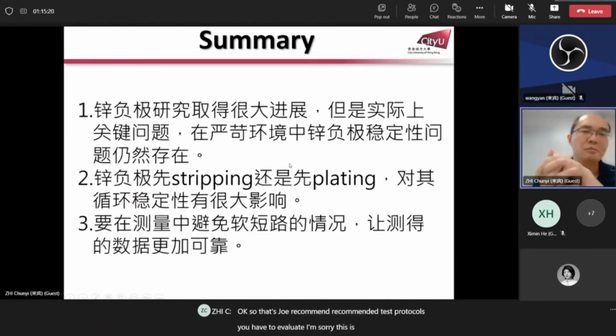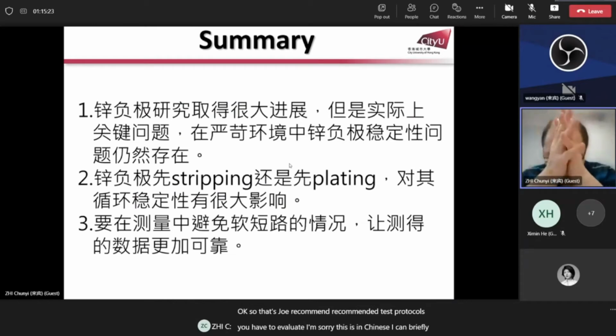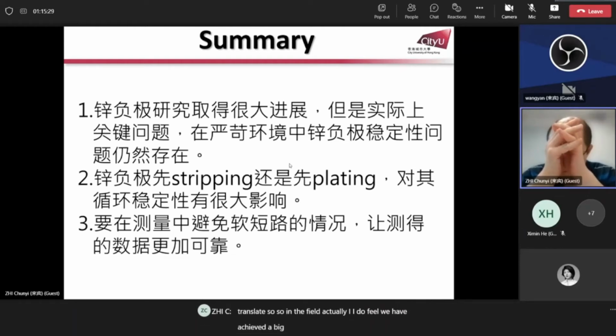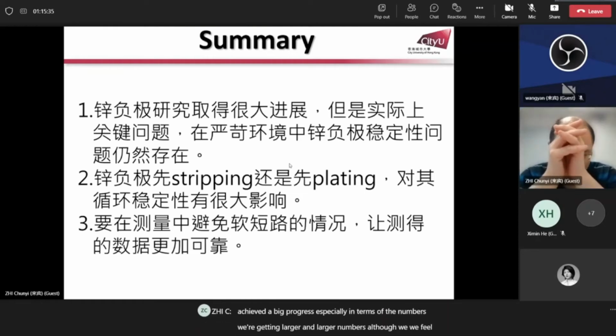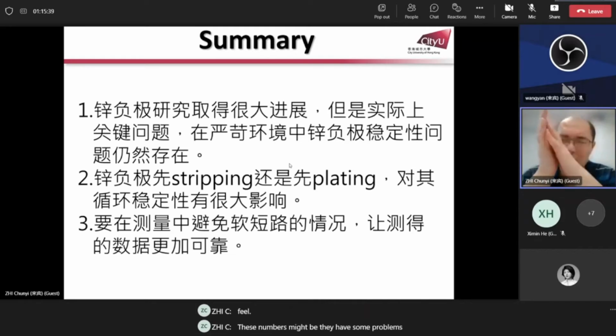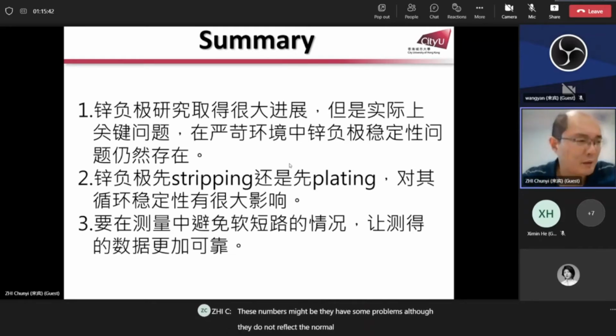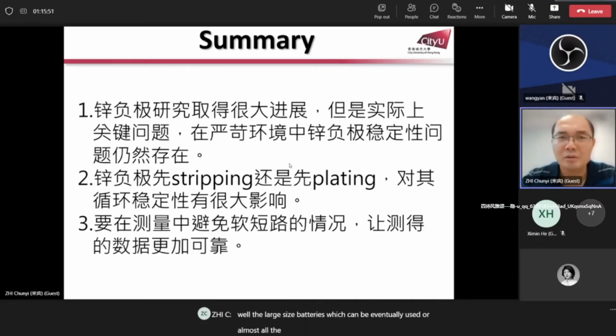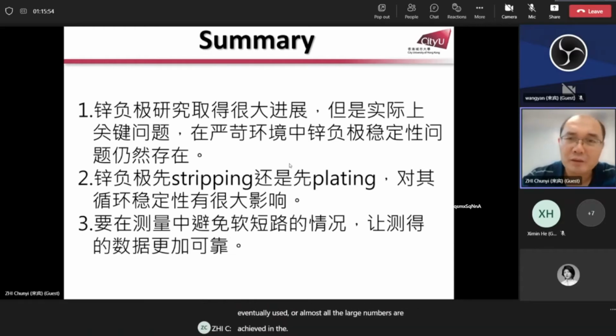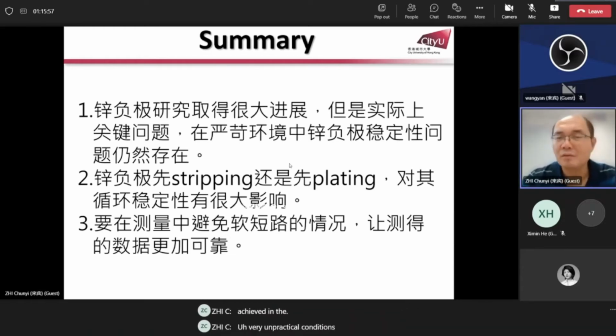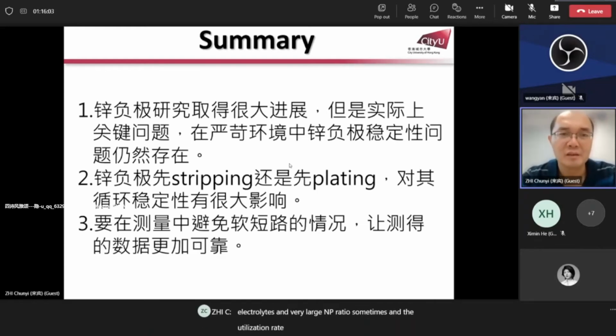I'm sorry, this is in Chinese. I can briefly translate. So in the field, I do feel we have achieved big progress, especially in terms of the numbers. We're getting larger and larger numbers. Although we feel these numbers have some problems, they do not reflect the large size batteries which can eventually be used. Almost all the large numbers are achieved in very unpractical conditions with a large amount of electrolyte and sometimes a very large NP ratio, and the utilization ratio of zinc is very small.